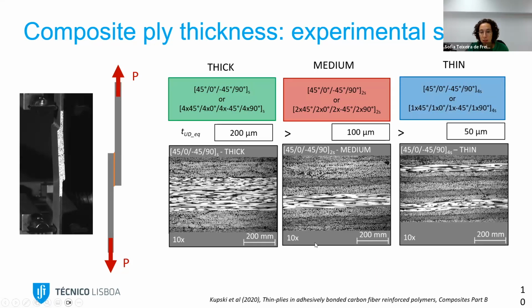So as you can see, these are images all with the same scale. And you see that there is a decrease in the thickness of each ply of the composite. One ply is here, the second one only this one or this one, and the third one is even thinner. So in this one we had 50 microns of ply thickness, which is considered an ultra thin composite.